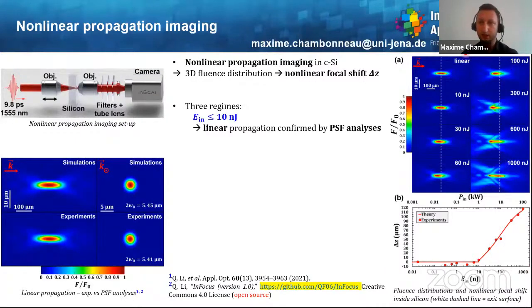So here on this data on the right, one can distinguish three different regimes. The first one is at very low input pulse energy, the linear propagation regime, which was somehow confirmed by some simulations that we carried out with the model, which was developed recently by my colleague Qingfeng Li, which is open source and thus open access. And if you are interested in doing these kinds of simulations, please feel free to note those two references. This might be useful for many applications, actually.